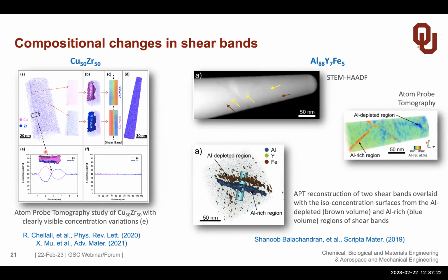And we have also studied this in more detail, and we have found that within the shear band, by using atom probe tomography, a technique where you can find the nature of an element or of an atom in a structure, and also its atomic position. When you do that, you can see there is a shear band in a small tip, which you can observe over here, where the structure and the composition has changed. And you see there's an enrichment of copper on one side and a depletion, and correspondingly for the zirconium in this binary system. This has also been found for another ternary metallic glass as well.